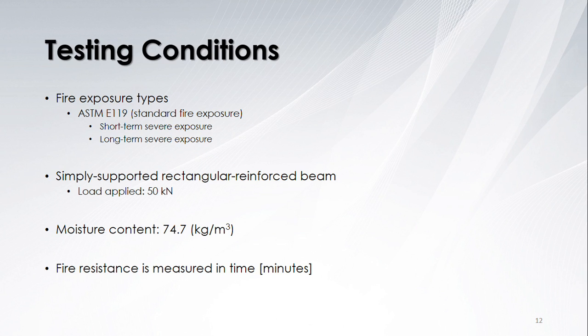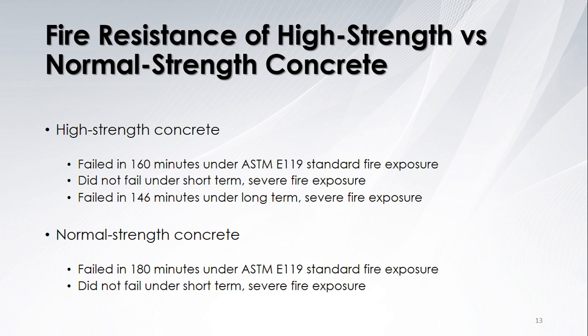Testing Conditions: The simply supported beams are tested in three types of fire exposures — ASTM-E119, which is standard fire exposure, short-term and long-term severe fire exposure. The applied load is 50 kN, moisture content is around 74 kg per m³, and fire resistance is measured in minutes. The high-strength concrete beam failed at minute 160 under standard fire exposure, and at minute 146 under long-term severe fire exposure, but it survived the short-term severe fire. On the other hand, the normal-strength concrete beam resisted the fire a little longer, failing at minute 180 under standard fire exposure. The normal-strength concrete beam also survived short-term severe fire.